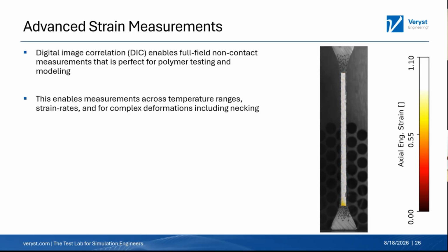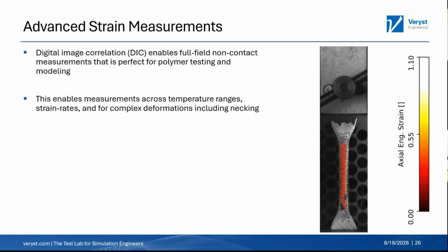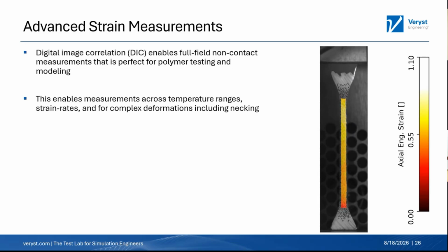The PETG in this case shows a very uniform deformation where we don't see what we call necking, but we can see that in this test, and you can use that to analyze data in different ways. So we do this for the majority of the tests we do here at Veryst Engineering. We use commercial software to do this, and it helps us get accurate data at all sorts of conditions using the same method. And so we find it to be a very powerful tool for selecting material models and getting data on polymers.